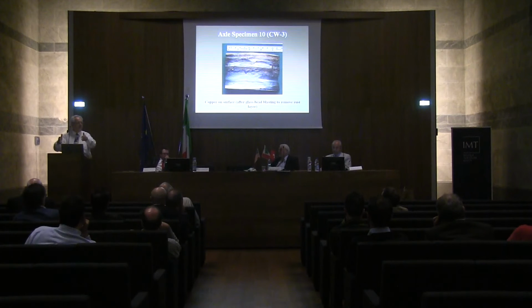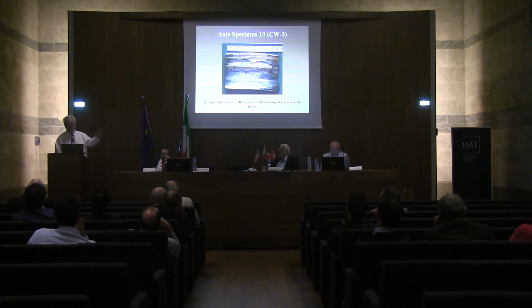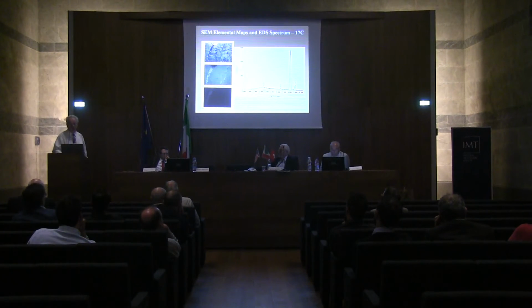The failure always starts in the center because the temperatures are highest, the stresses are highest in the center. But the fracture is banged up, and so the fracture is destroyed, and your first thought is, what can I prove without the origin? Well, in this case, it was no problem because there were secondary cracks all over the place, loaded with copper. So here's an example of SEM elemental maps and EDS spectrum on sample 17C.